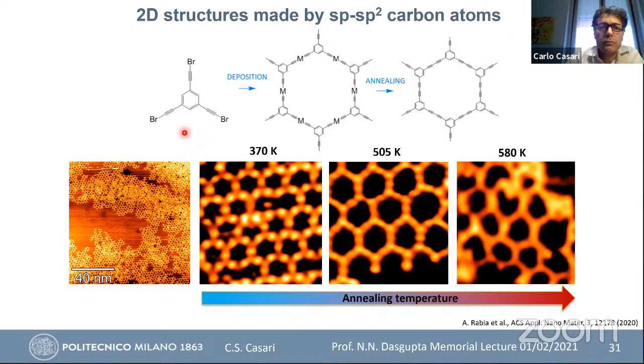We did the same, again in collaboration with Wei Xu, with this kind of precursor, able to produce a two-dimensional network. In the same way, by evaporating, you have a release of the bromine, and gold is catalyzing this kind of structure. Then if you anneal, you should have this kind of structure. So this is what we observe by increasing the temperature. Of course, we observe the release of the gold atoms, but also some distortion of the structure.